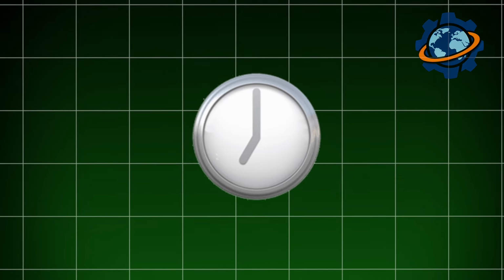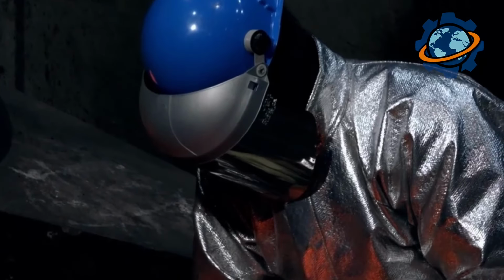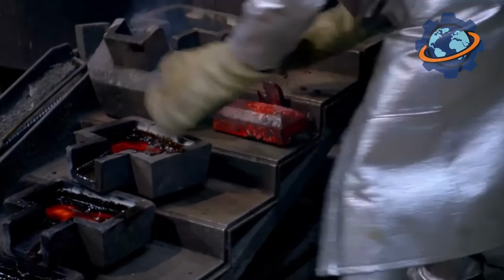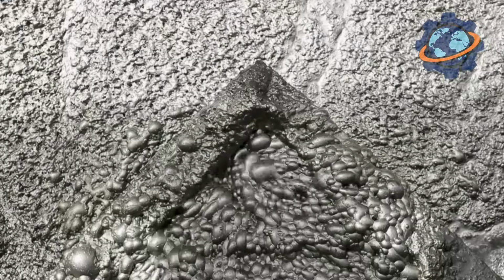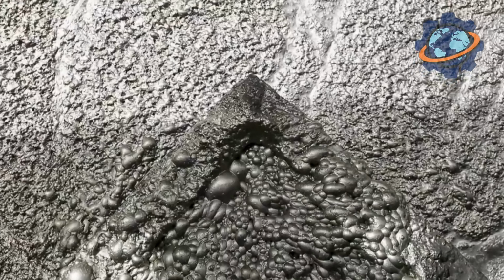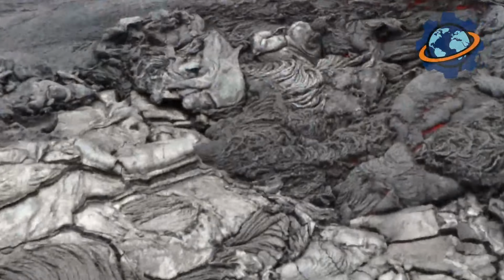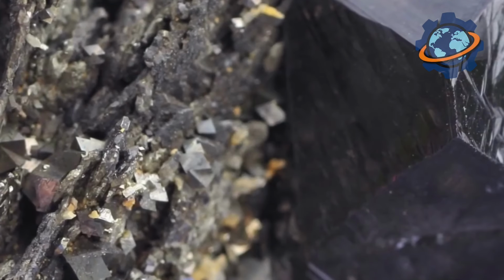The beam is held in the bath for 1 to 2 minutes. Then it's pulled out. Excess molten zinc drains back. In air, the coating quickly solidifies. The surface becomes silvery, matte, with the characteristic pattern of crystals, zinc flowers. Coating thickness from 2 to 8 thousandths of an inch. That's just fractions of an inch, but it's enough.